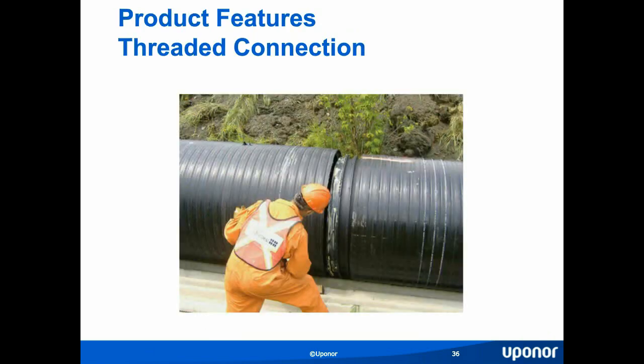We also have, in addition to our welded joint, a threaded connection. The thread is connected in our factory by removing the outside profile wall of one end of the pipe and the inside profile wall of the adjoining pipe. That's the advantage of a helically wound pipe: you can create these threads. The threaded joint is not leak-free, but it is silt-tight, and it's an excellent application for culverts because they don't need to be leak-free in 99% of cases. And because it can be performed by a contractor without having an Uponor technician there to weld it, it's very contractor friendly as well.